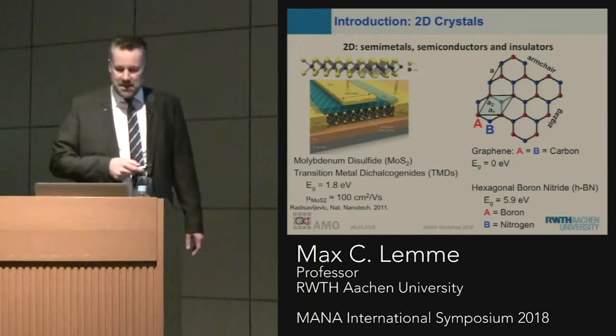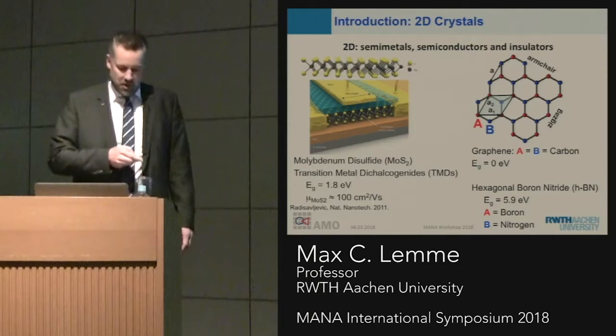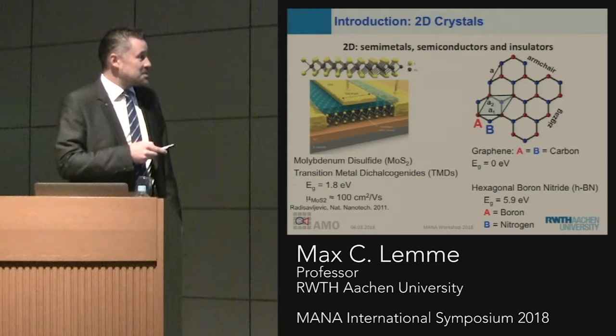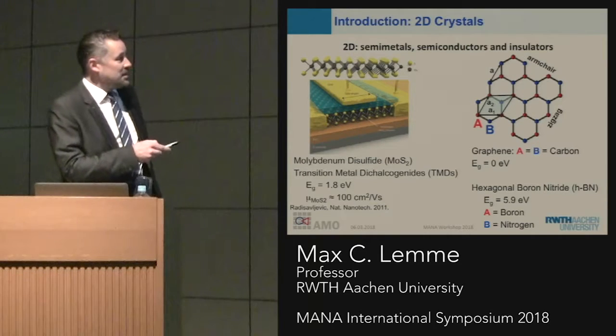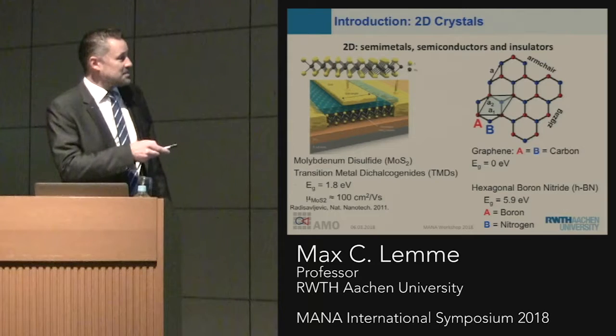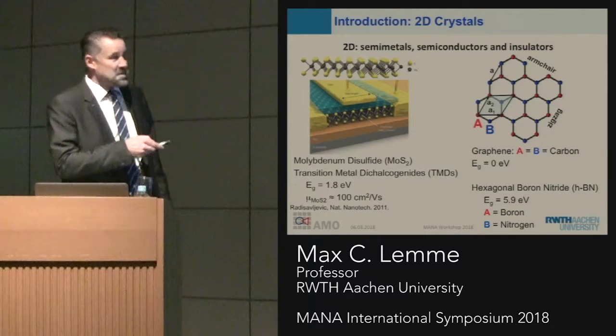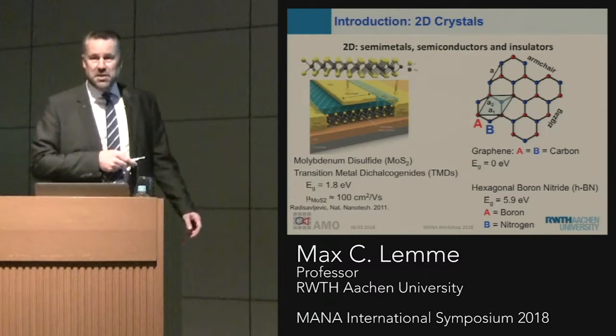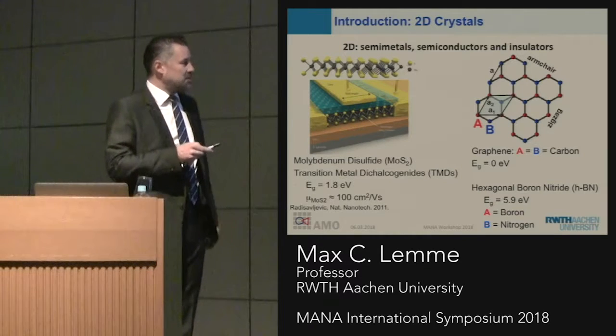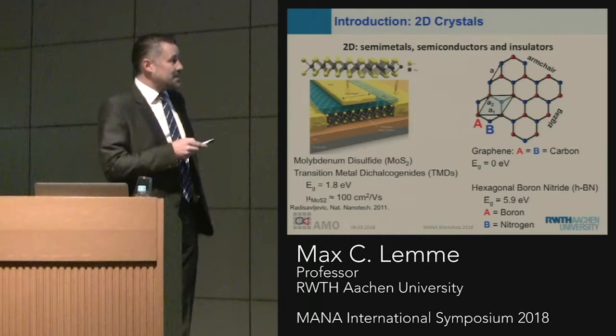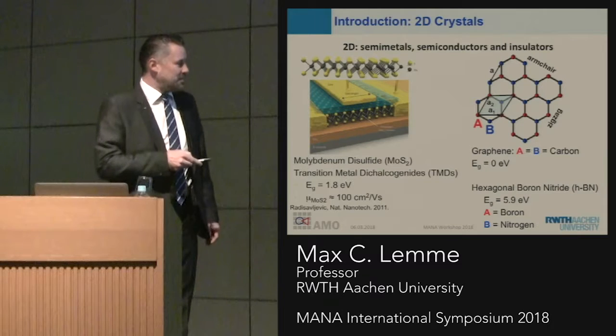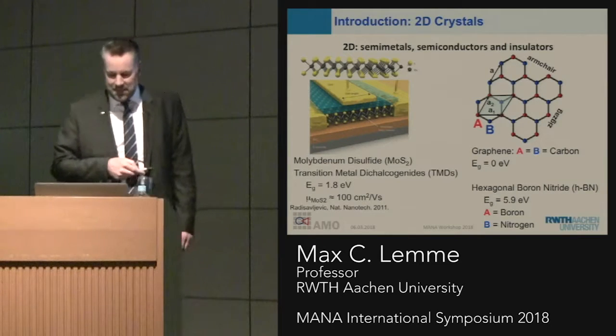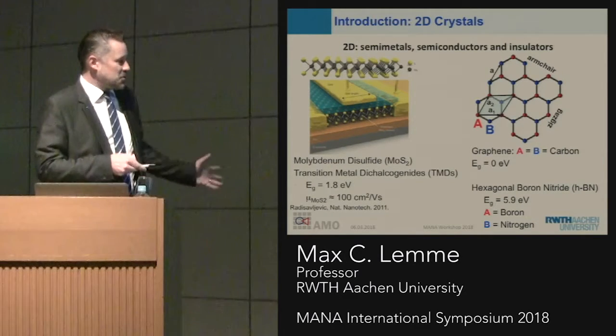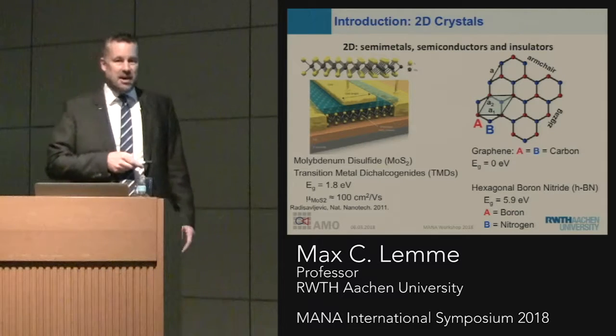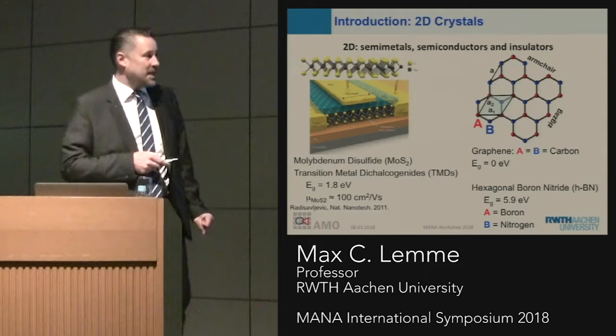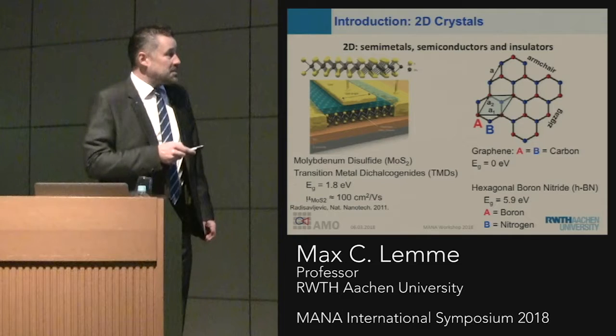Then we also have these so-called transition metal dichalcogenides, and one example is here. This is molybdenum disulfide, where we have a core of molybdenum atoms covered on both sides, in this case with sulfur atoms. And this material, for example, is a semiconductor, and in its single layer form, we have a direct band gap of 1.8 eV, and people have measured mobilities in this material of several hundred centimeter square per volt second. But this is not all.